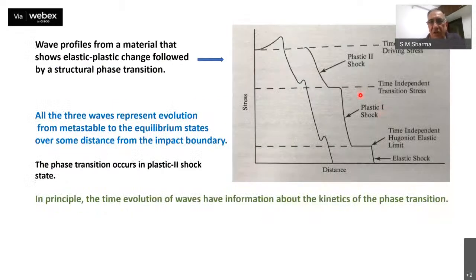And this is how the shock wave will look. This is for a thinner plate. You would see a shock here and then another here, and this is the final equilibrium value that it will have. So this is the equilibrium elastic limit, which we call the Hugoniot elastic limit, and this is then the plastic shock. Okay, and then it takes the value that was expected, and then it undergoes, in that plastic state, another phase transition, and then it takes it to its final equilibrium value.